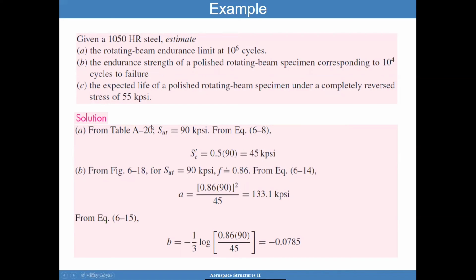So we can do that quickly. I know the ultimate tensile strength of this material. So times 0.5 gives me the endurance limit for a rotating beam. And then looking at the literature, you're going to find that f is about 0.86 at 1,000 cycles or so. And so you can use these calculations to plug this in here, and then you get an A of 133. The exponent follows very similarly. It's basically the same ratio without the square, and you get a B of -0.0785.